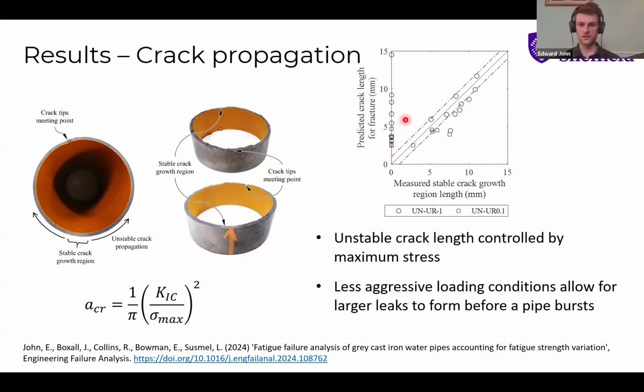There were a relatively large number of tests where we couldn't identify a stable crack growth region. So this could just be that it wasn't clear when we looked at it under a microscope, but also these tests all tended to be those which failed a bit prematurely. So there might be something else going on there. But basically what this shows us is that less aggressive loading conditions with lower maximum stresses allow for larger cracks to exist, which means that effectively you can have larger leaks forming before a pipe bursts.